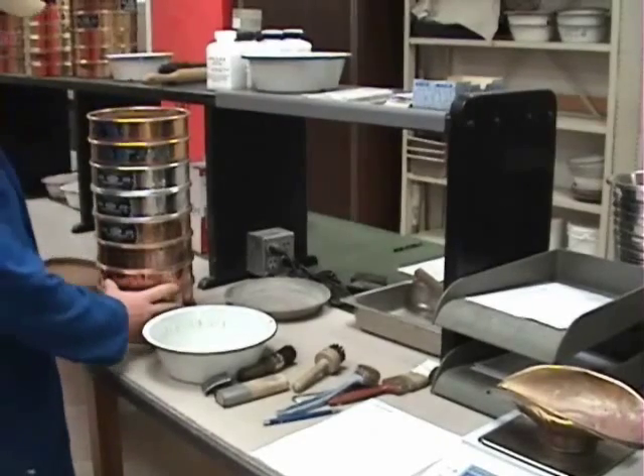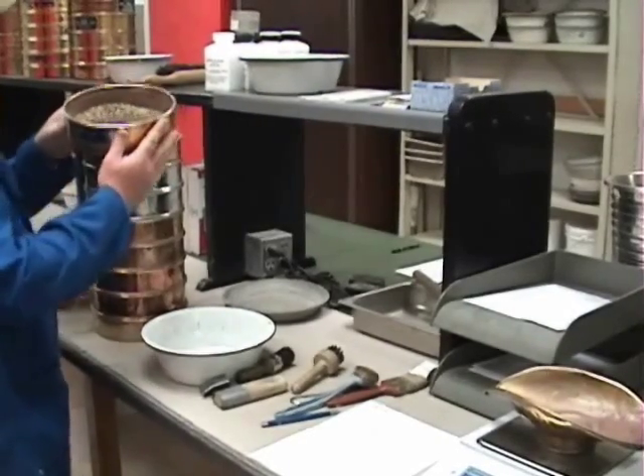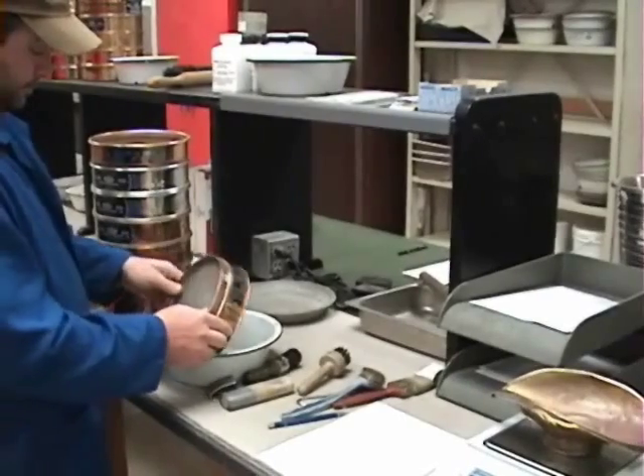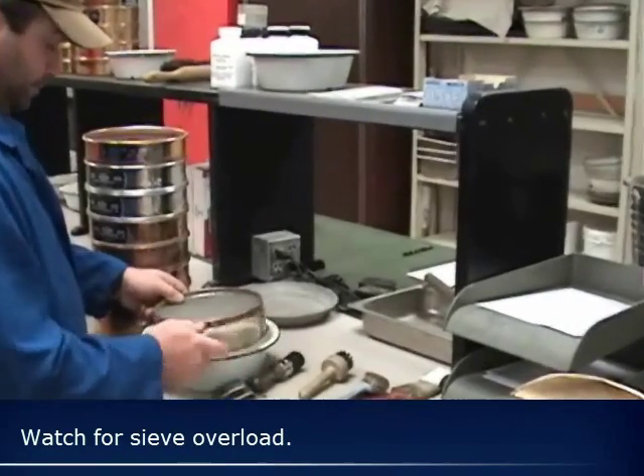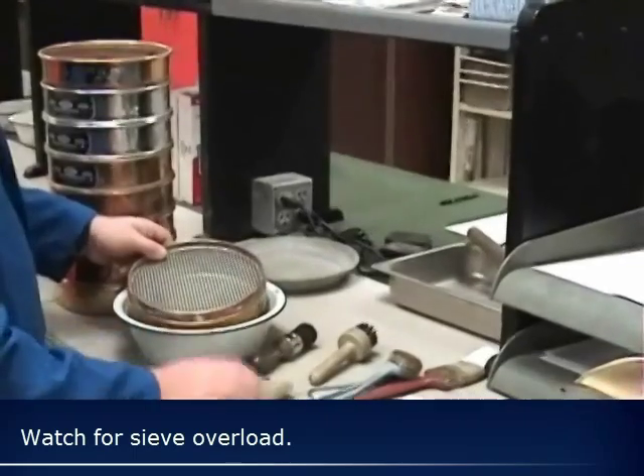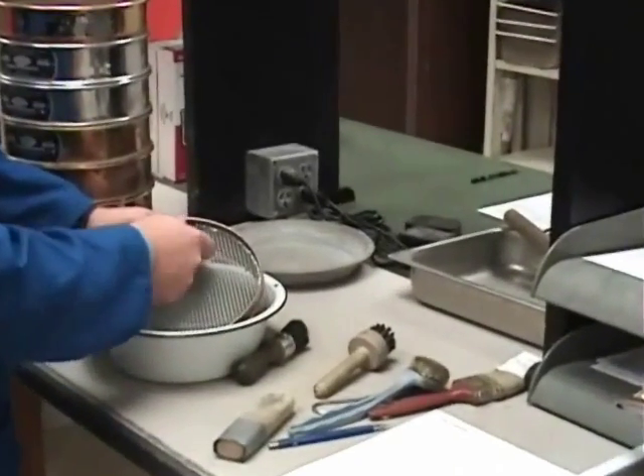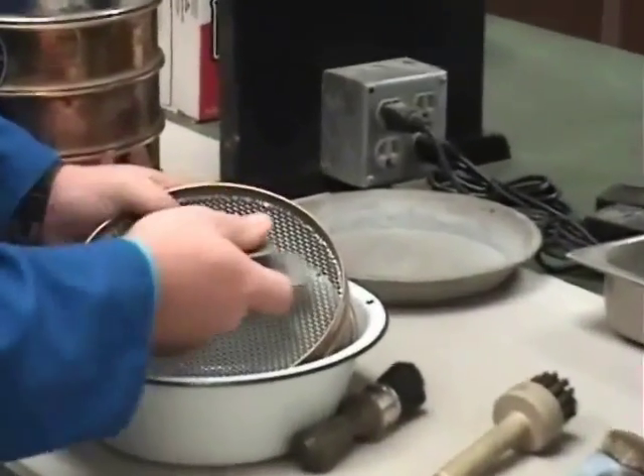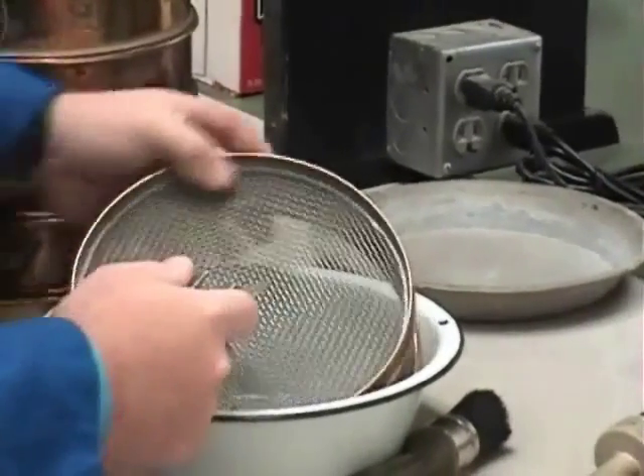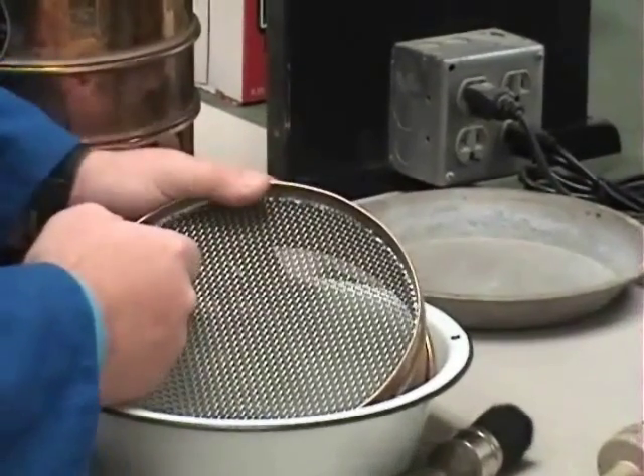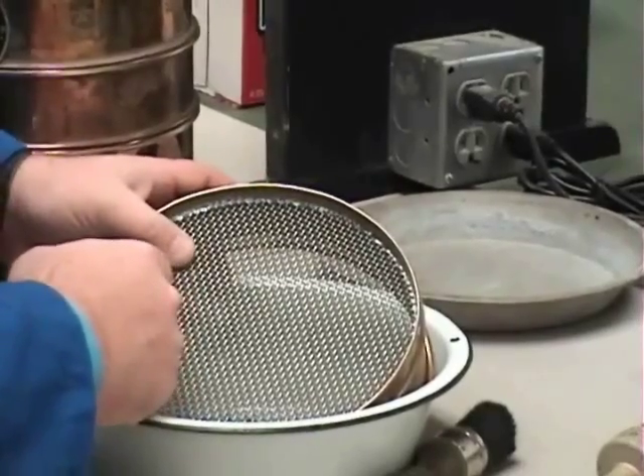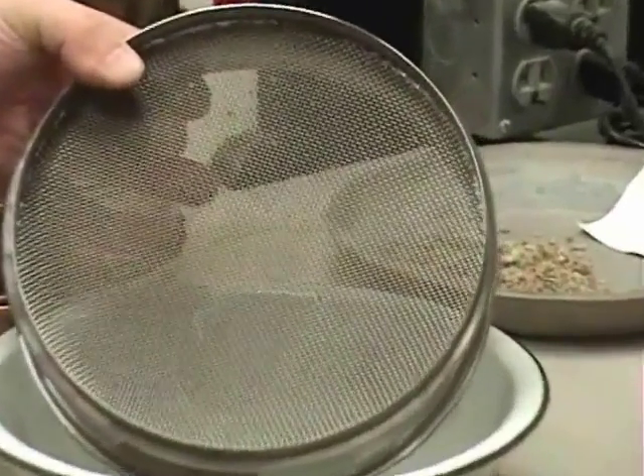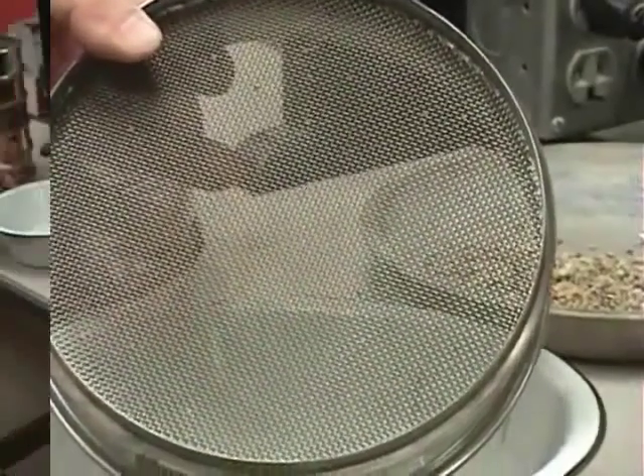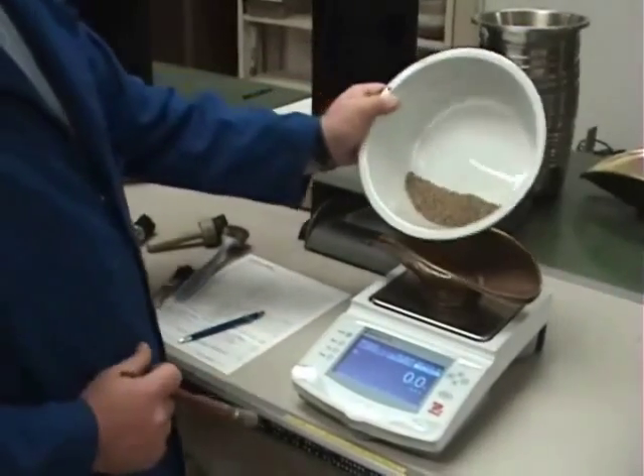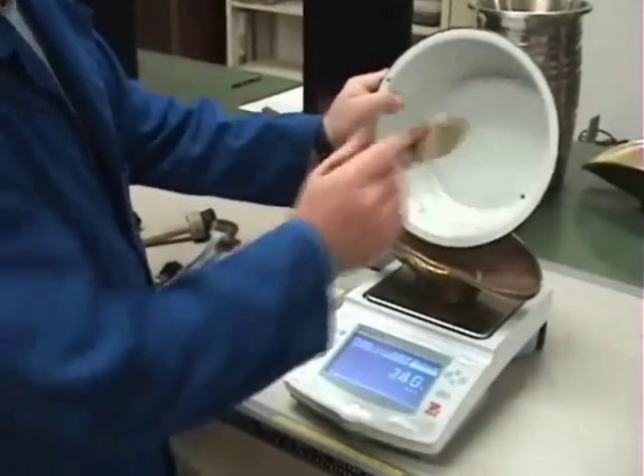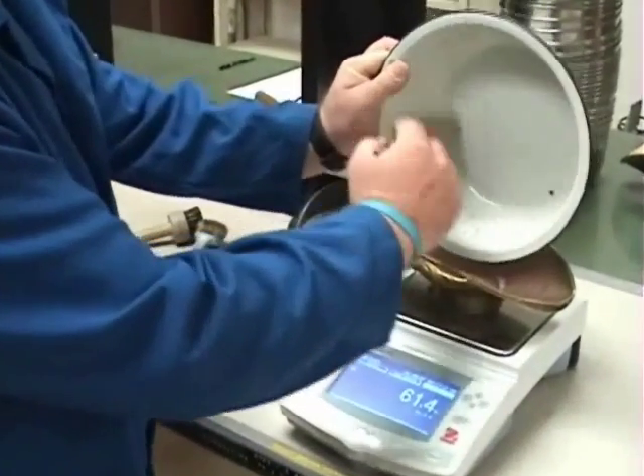Take your first sieve off of the nest of sieves and pour the material into a suitable container. Then, tap the side of the sieve to dislodge particles that may be stuck inside the mesh. Use an appropriate tool to push the material through. This is mainly on the coarser sieves. Weigh and record the material retained on each sieve. Repeat the process for the remaining sieves.